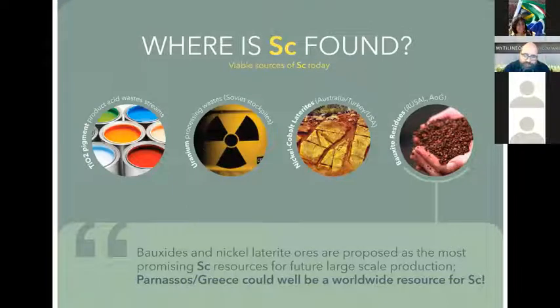But at the same time, you have the bauxites that are used for alumina production, where scandium is enriched in the bauxite residue. It's not leached during the Bayer process. So all the scandium ends up in the bauxite residue, having essentially doubled its concentration from the initial ore. So there are bauxite residues in the world which have several hundreds of ppm of scandium. Notably, Rusal has already produced a pilot plant for extracting scandium from bauxite residue.